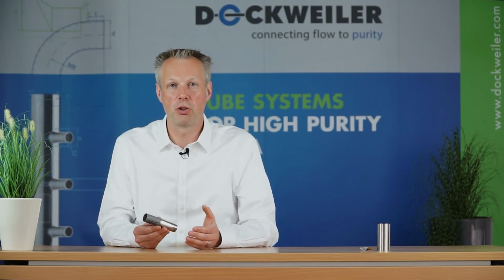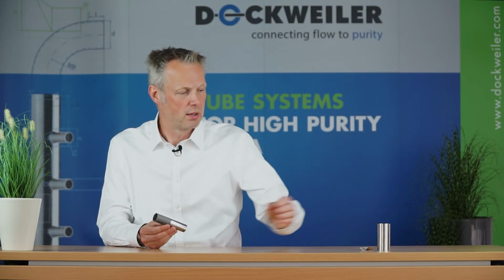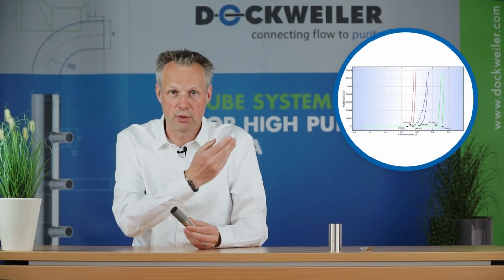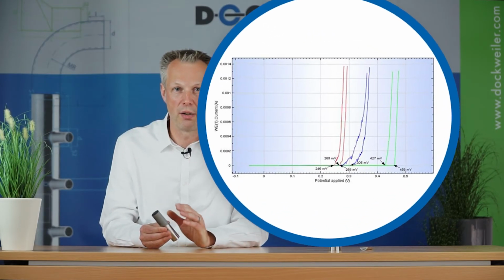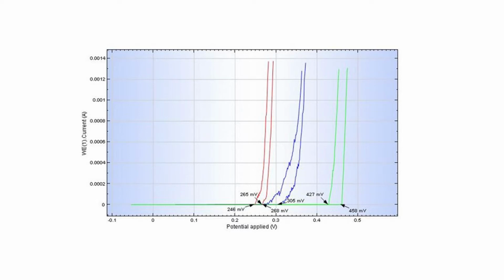And what is the actual quantitative effect on this? We took the bright finished version and did an ASTM G61 test that you can see up here. You will figure that you have roughly a CPP value of 250, which is actually pretty low. Further down the road, when you start to take off the surface, which we do by electropolishing, first, let's say 10 micrometer, it will reach a value of roughly 300. So it's getting better. We take off contaminated surface structures and we get a higher CPP value.